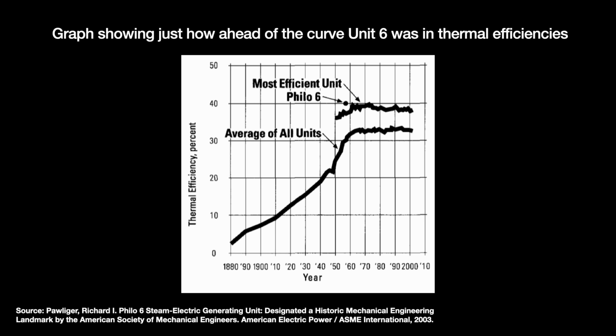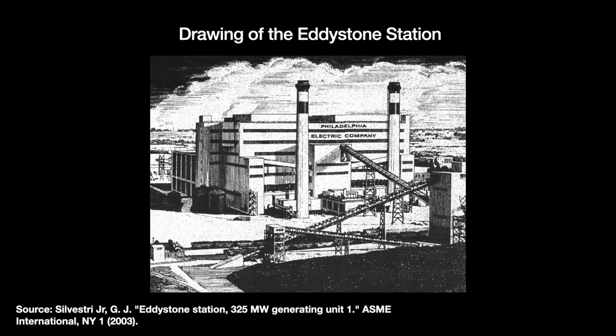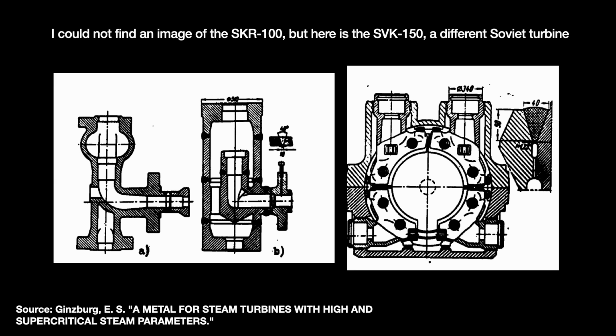After Philo Unit 6, a second supercritical power generation unit fired up in 1961, Eddystone Unit 1. Built by the Philadelphia Electric Company, Eddystone steam reached operating temperatures of 649 degrees Celsius and pressures of 34 megapascals. The Soviets also got into the fun, launching a prototype turbine called the SKR-100 in 1968. It achieved steam conditions of 30 megapascals and 650 degrees Celsius. But Unit 6 led the way.